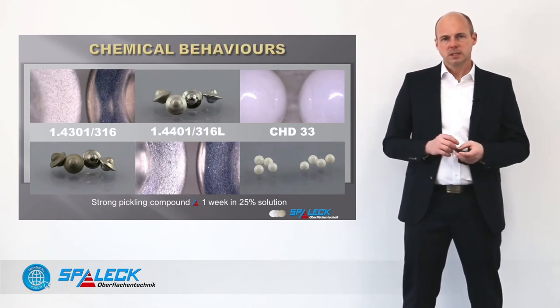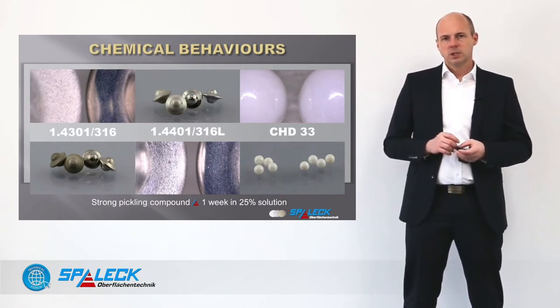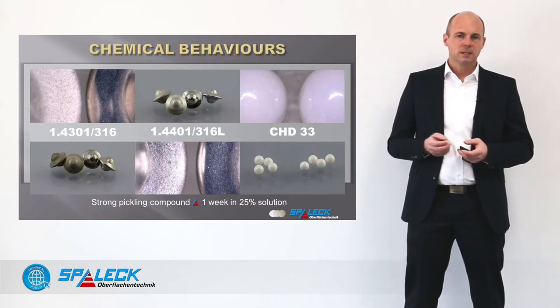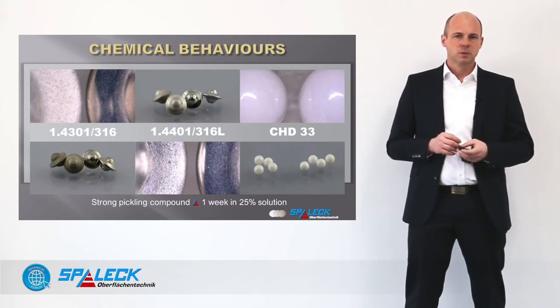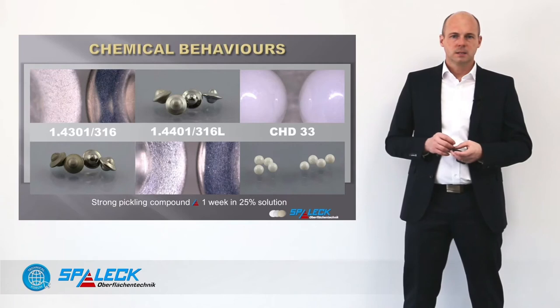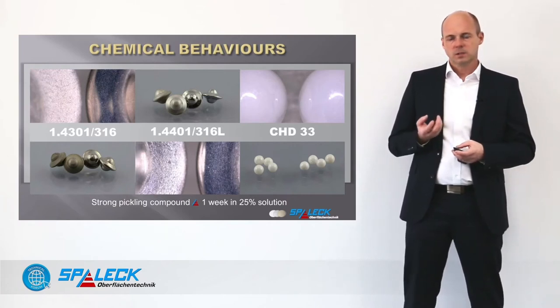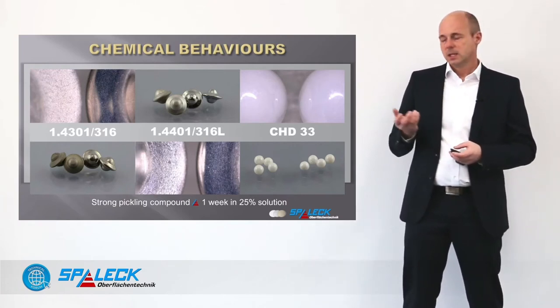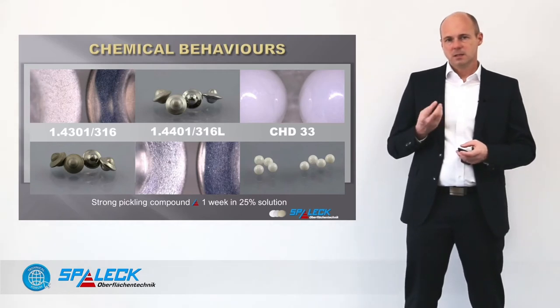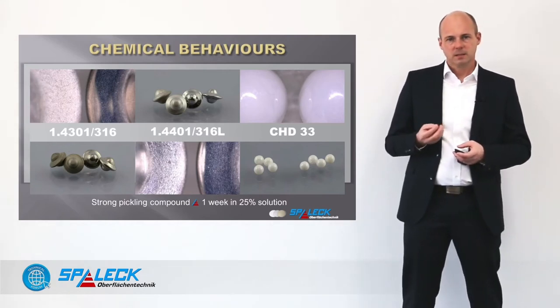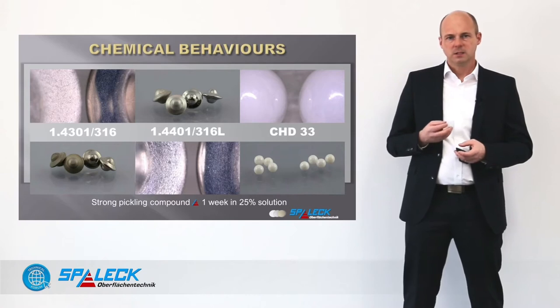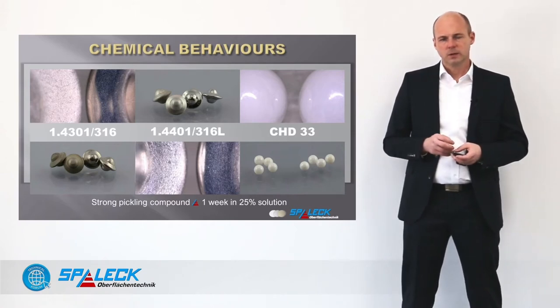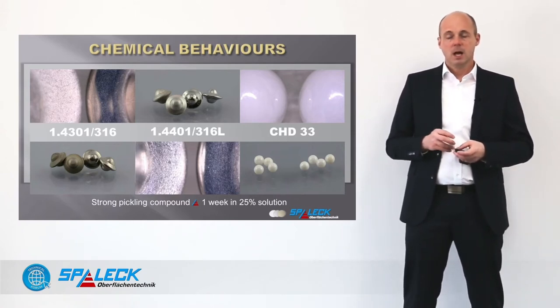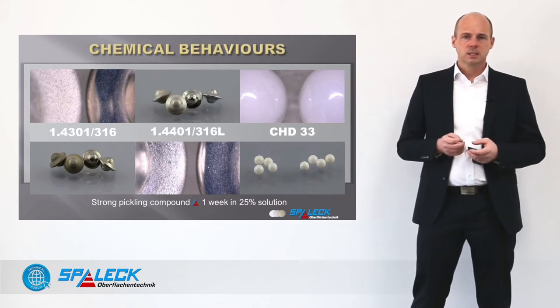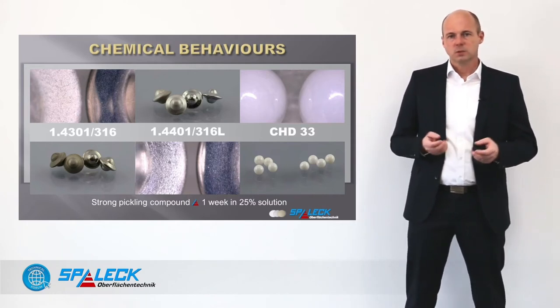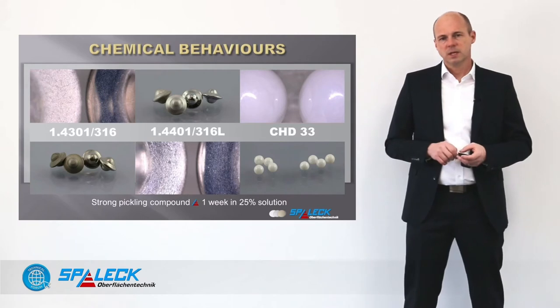just 316, which is not common, but still some people use it. With the results that we see here, the strong acid is terribly attacking the surface and is basically destroying the material after a very, very short period of time. A higher chemical resistance has a 316L, which is more the standard in the industry since many, many years.